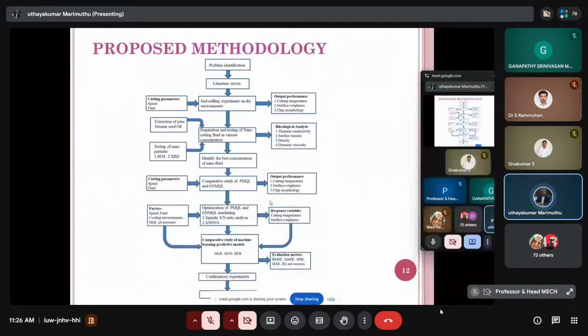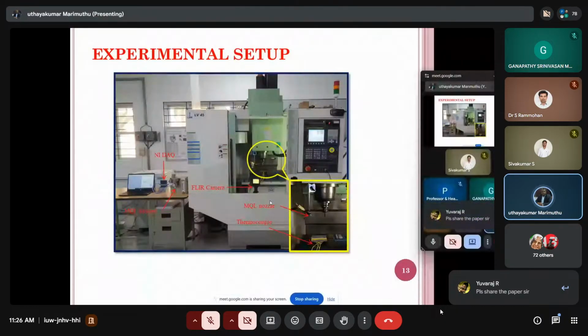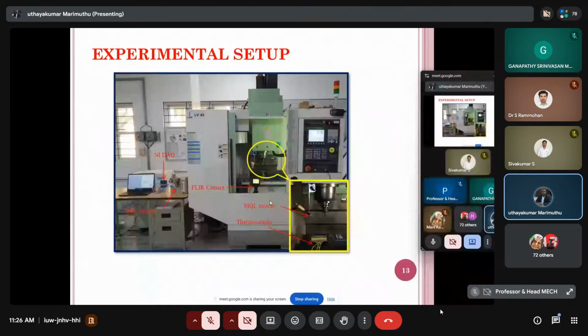Now this is the experimental setup through which we get the results. This is about the LMW high-speed milling machine, and we have used the FLIR camera. This MQL is an additional attachment that we made on our own, and it will pass the coolant to the cutting zone. The thermocouple and FLIR camera both are used to measure the temperature during the machining.